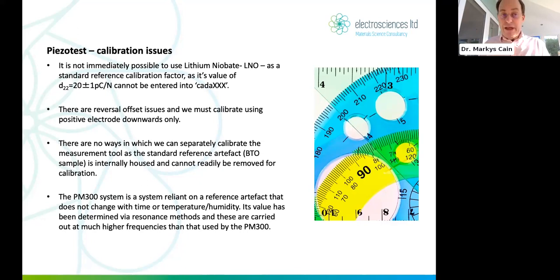It's very difficult in the piezo test machine, if not almost impossible, to separately calibrate the system because the internal standard reference artifact, which is BTO typically, is internally housed. You can't move it. I mean, you can take it apart. It's all soldered in. It didn't used to be. It used to be brass electrodes and so on, but it's all soldered in now. So it's very difficult to remove, to calibrate exactly, which means you need to use external artifacts which are calibrated in other ways as your calibrant system.